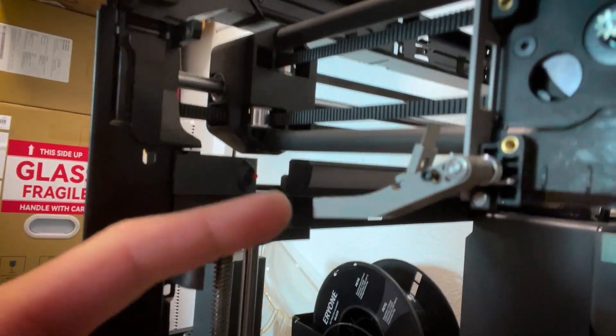That sums up my experience with the Bambu Labs printer with a clogged extruder. This is one of the things I haven't mentioned in my previous video when I reviewed the Bambu Labs P1P because it just happened to me this morning. If you're not planning to print with flexible filaments then you don't have to worry about this, but I've also had this happen on my printer at work where there were issues with TPU — the print started and then nothing came out, just very thin strands of TPU. Luckily on the work printer I was able to pull the TPU out. What you have to do instead of cutting the TPU — do not cut your TPU if it's stuck in your extruder — is remove the Bowden tube and then grab the TPU from the top of the extruder and pull it out as you try to de-extrude your filament.